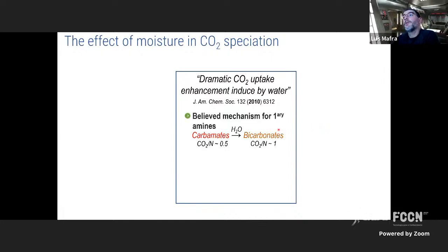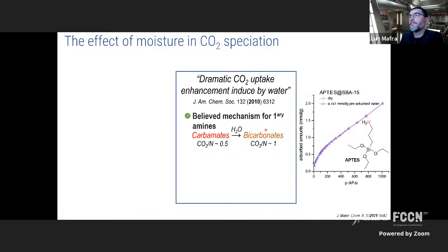When we read the paper, the explanation was that carbamates formed when you absorb CO2 in these materials become bicarbonates once you add water, which makes sense. It increases the CO2 capture capability because the stoichiometry changes and you can now accommodate 2 times more CO2. But when you compare the isotherms of dried samples with samples previously exposed to water and then to CO2, we see that the isotherms overlap. We don't see much change here.